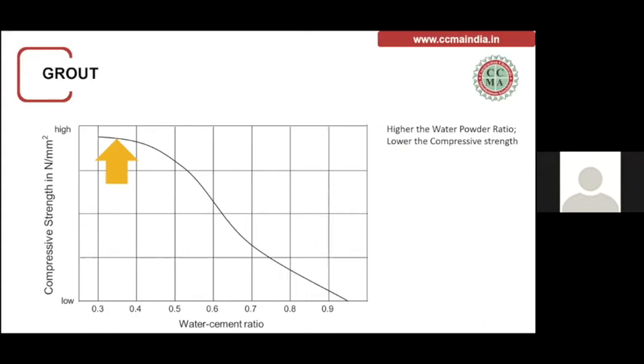The compressive strength of grout is directly connected with the water powder ratio. In this chart you can see that if the water powder ratio is high, the compressive strength would be low. So this is inversely proportional. We should always keep in mind that wherever we have to mix water, we should pre-measure it and ensure that excess water is not added, because if excess water is added, there is a possibility that the compressive strength of the grout will reduce and the end result would not be met.